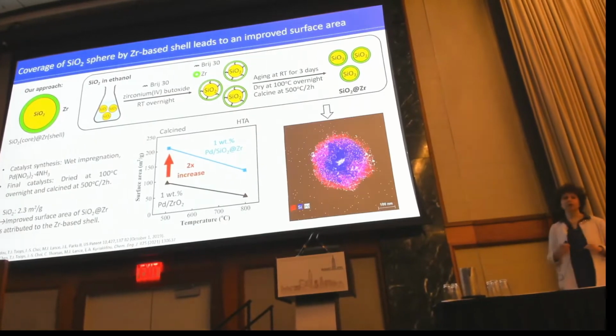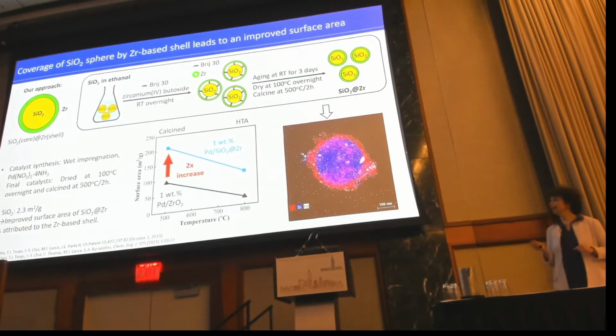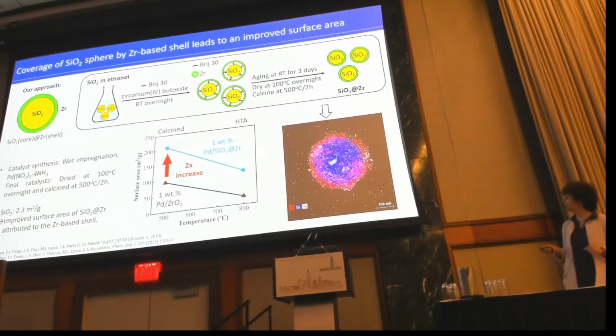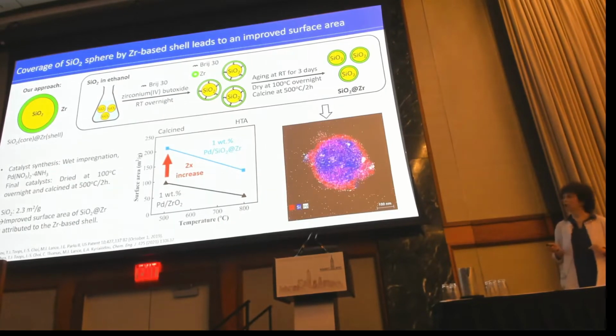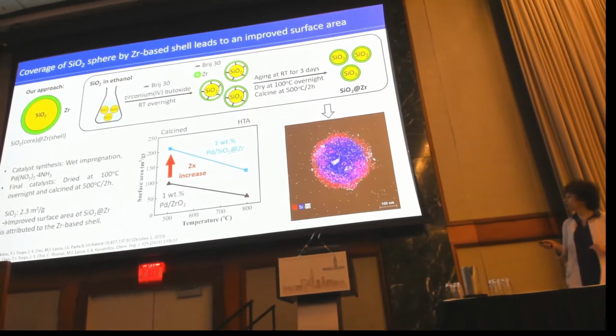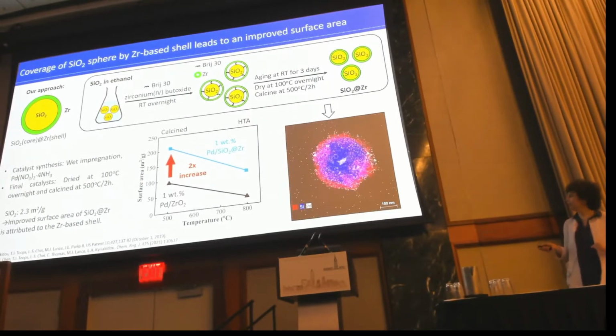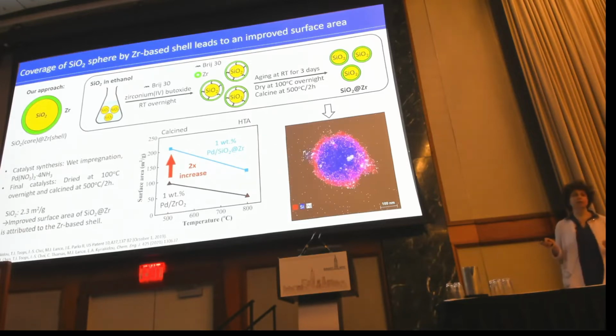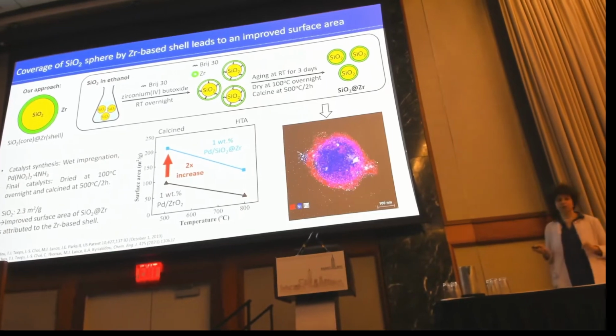And a very important piece of information here is that the surface area of this material is different than the surface area of the palladium on zirconia. So this plot here shows the surface area of the palladium on the core-shell support material and palladium on zirconia, when these materials are calcined at 500 degrees C for 2 hours and when they are hydrothermally aged at 800 degrees C for 16 hours. So what we see here is that the core-shell material has twice as big a surface area compared to the palladium on zirconia. So this was very promising.